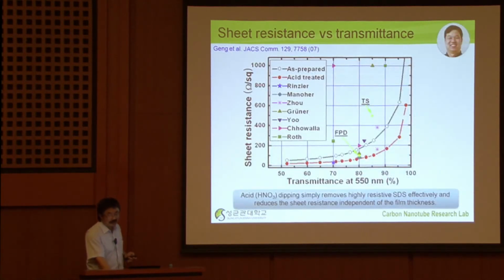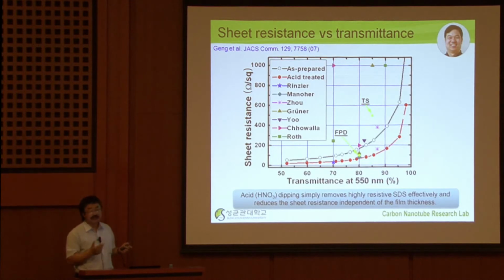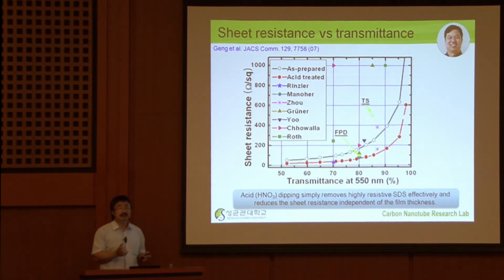So you have to do something, and actually what we did is we dispersed CNTs using a surfactant such as SDS or NaDBS, because SDS is basically an insulating surfactant, and we want to remove it. We remove it by simply acid treatment by nitric acid in this case. You see by a simple nitric acid treatment, the sheet resistance is improved quite significantly, independent of the thickness. So this is a simple way of removing SDS. Usually people believe SDS can be removed by simply washing in water, but that is not the case here, because the nanotube in this case is simply a random network, and they are entangled with each other, including this SDS. So by simply washing, it doesn't work. So you have to do something, and then we found this acid treatment is a very good approach.